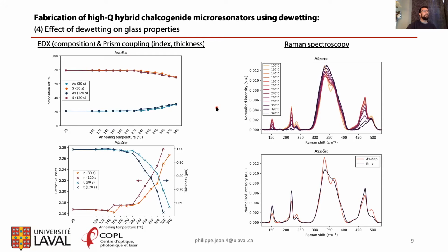Next, before actually going on to chips, we did the deposition on glass slides, and we did material characterization to have an idea of how the dewetting will affect the material properties. You can see here EDX, which gives us the composition as the annealing temperature increased. Here you can see on the left the refractive index, and on the right the thickness, that were measured using a prism coupling method. Finally, here you can see Raman spectroscopy curves that give us an idea about the molecular composition of the glass.